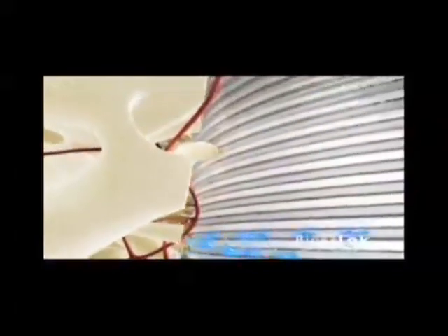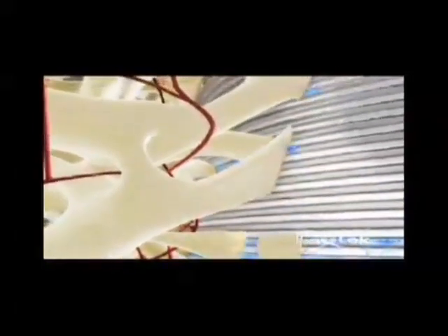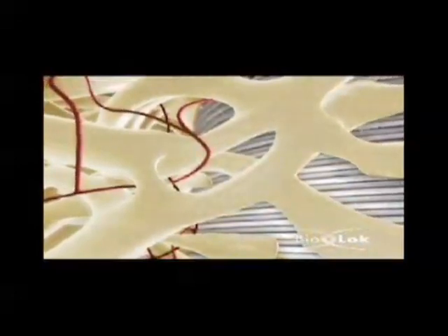Once a stable soft tissue seal is formed, osteogenic cells are allowed to form a mineralized attachment to the implant. Laser-Lok's 12-micron cell channels direct osteogenic cells to migrate along and produce a strong horizontally organized bone matrix within the channels, increasing resistance to loading forces.